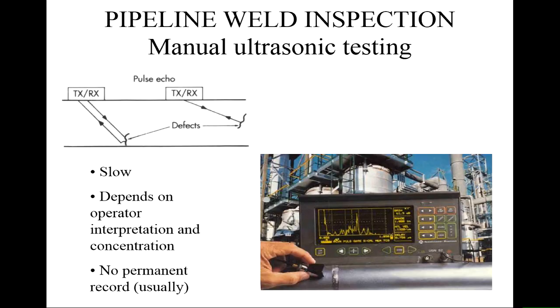Ultrasonic systems are also very commonly used. Manual systems are largely used for corrosion monitoring, but they are also used occasionally for weld monitoring. So the idea is that you have a transducer, which is an ultrasonic crystal which is vibrated by an oscillating electric current, or an oscillating voltage across it. And those vibration pulses are acoustically coupled into the pipe, so you have some sort of contact, some sort of medium to take that vibration and translate that to vibration in the pipe. And then you get a sound wave that goes through the pipe, and it's reflected back off the back side of the pipe or off a defect, and you then detect the reflected or